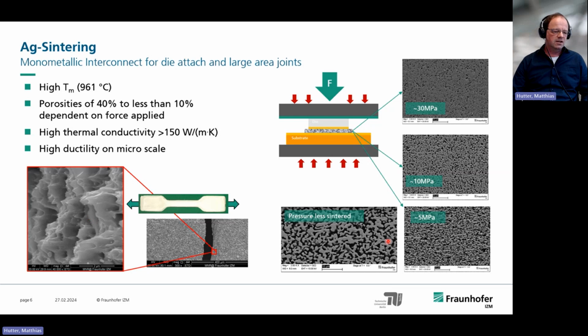And you see, you can adjust the micro porosity by simply applying different forces during the sinter process. So if you do it without any pressure, you receive quite high porosity, and the higher the force you apply during sintering, the lower the porosity. Here in this case, it's lower than 10%.